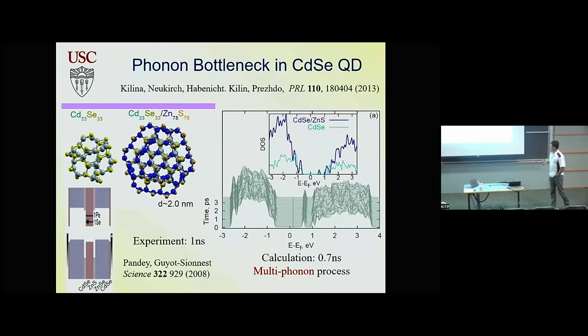And there's another feature of nanoscale materials, including quantum dots, which is these Auger-like processes, which are pretty unique compared to bulk semiconductors or molecules, because in nanoscale materials, you have two things that are happening together. You have high densities of states, like you have in bulk semiconductors, but also you have pretty strong electron-hole interactions, Auger processes, Coulomb interactions, like you have in molecules, because in bulk materials, you have screening and charges are far, but here they're close enough, but the densities of states are also high.